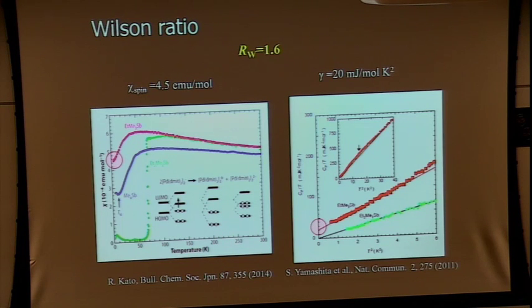And interestingly, we can compare the specific heat gamma and the spin susceptibility in the low temperature limit here. So you can calculate the Wilson ratio, and the Wilson ratio is 1.6, nearly exactly the same value as the previous spin liquid material. So two spin liquid materials show nearly exactly the same Wilson ratio. So we think that the two materials carry a similar kind of spin liquid, I think.